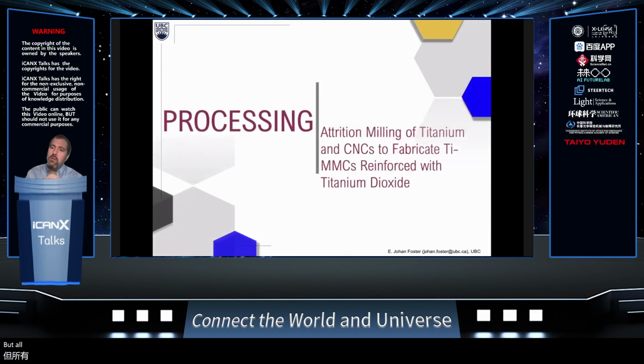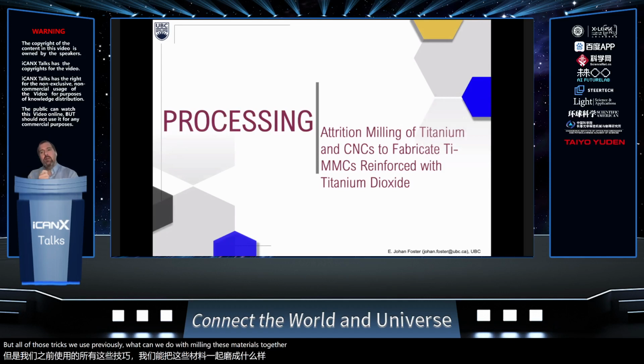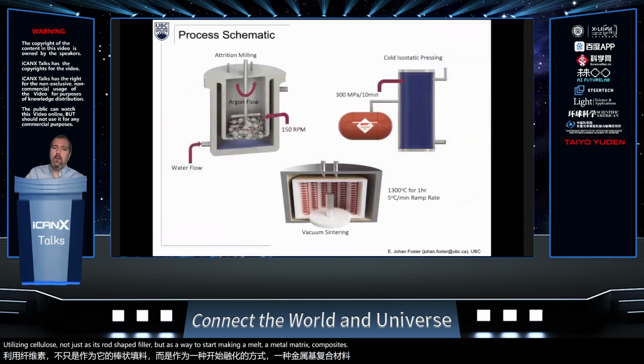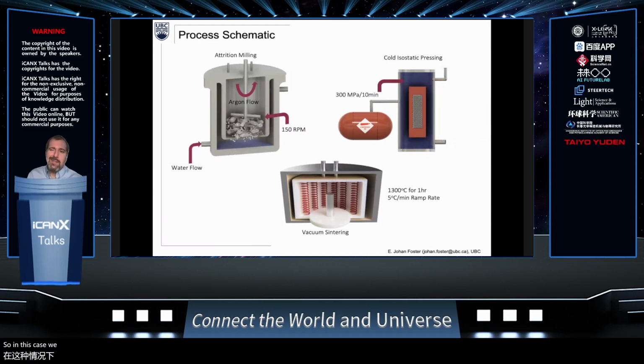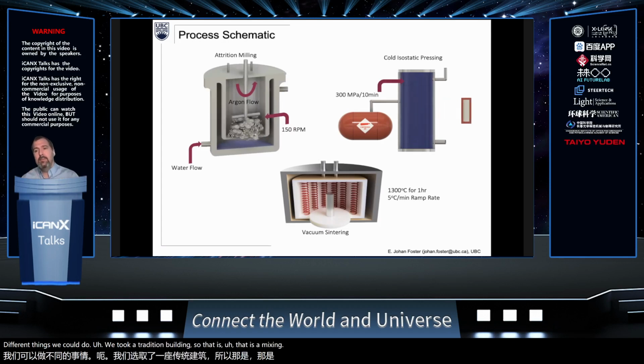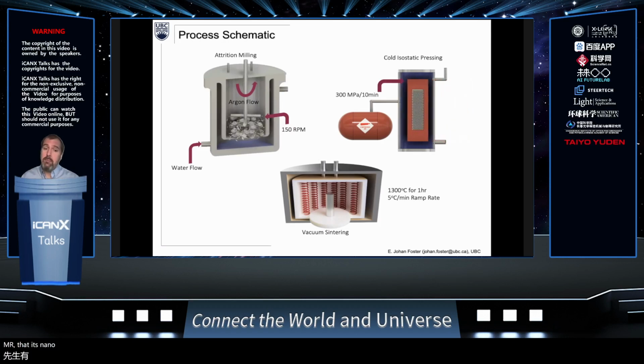But all of those tricks we used previously, what can we do with milling these materials together, utilizing cellulose not just as a rod-shaped filler, but as a way to start making a metal matrix composite? So in this case, we wanted to mix these together. We were wondering whether the cellulose nanocrystals would coat the titanium. And now this is after many, many tricks. We took attrition milling, so that is mixing the titanium powder and the cellulose nanocrystal powder together, and compressing that, using a cold isostatic press to compress it into a green body.